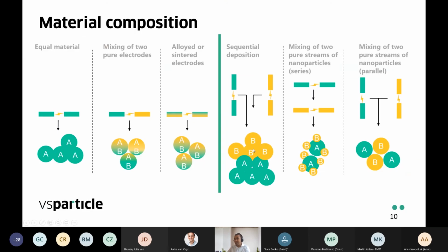We're very flexible in the types of materials that we can prepare. It all depends on the electrode configuration that we use. On the left of this solid green line, I show you the types of materials that we can prepare using a single spark generator. If we have electrodes of the same material, we can form monometallic nanoparticles. We can form alloys by mixing and matching these electrodes, but the elemental composition of these nanoparticles will then vary between the two extremes of the individual electrodes. We can form more accurate alloys by pre-sintering or pre-alloying the electrodes, and then the composition of the nanoparticles that we form are equal to that of the electrodes that we start off with.